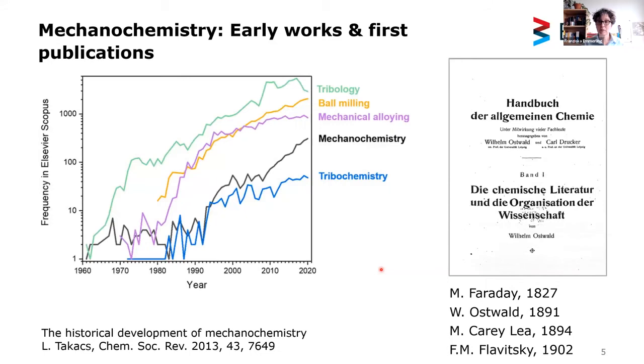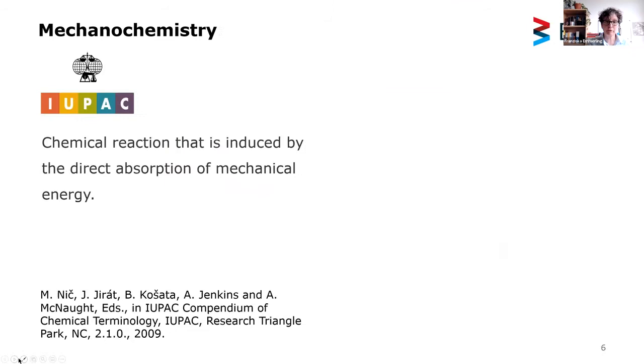If you look at the literature now, you can see that citations dealing with mechanochemistry increase, but there are also other terms around, like tribology or ball milling, and also tribochemistry, which refers to the interaction in solids. Nevertheless, there is a tremendous increase in the field, and there are reasons for it. If you look at the definition that exists at the moment, IUPAC defined mechanochemistry as a chemical reaction that is induced by the direct absorption of mechanical energy. So this is a very broad definition, and there are also some things that are unclear. How can we measure the direct absorption, for example, and so on.